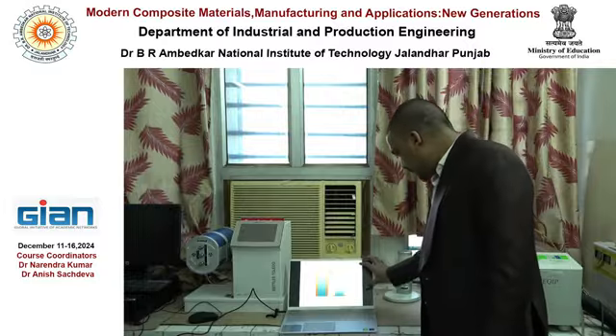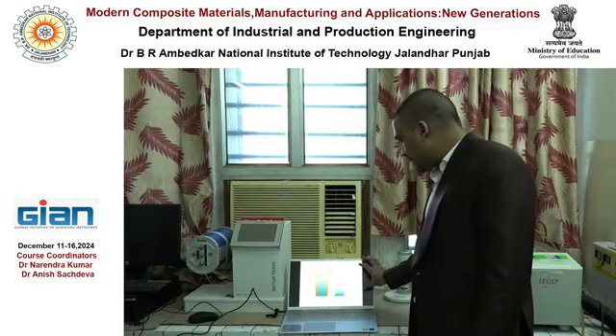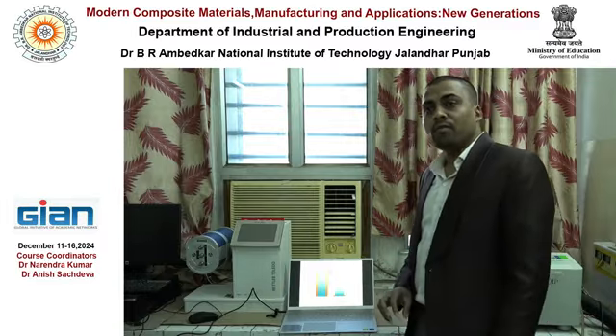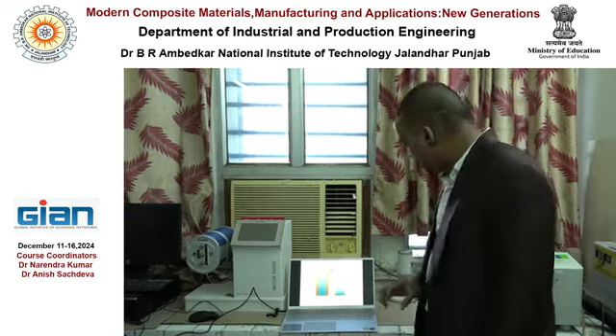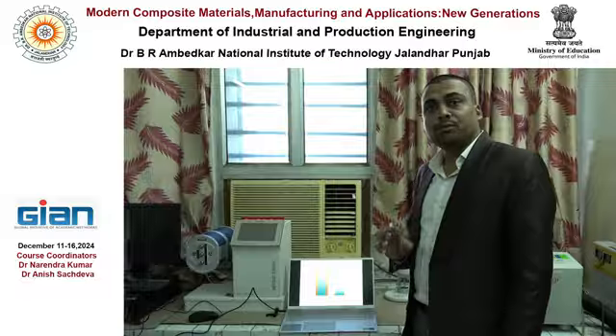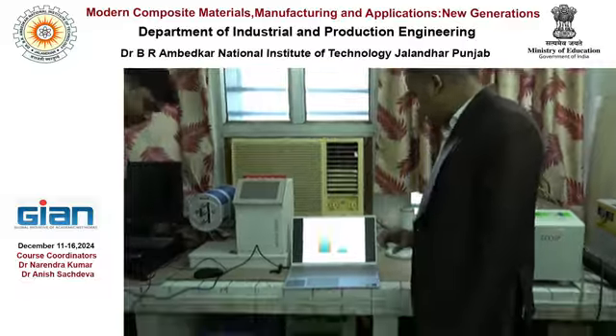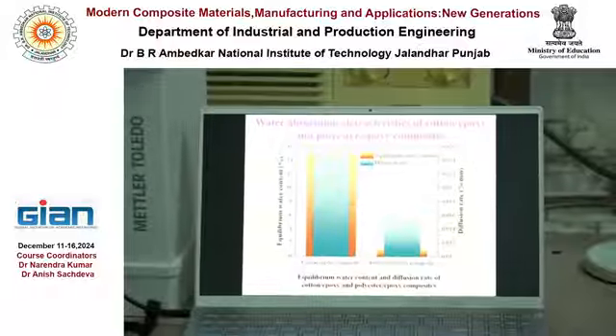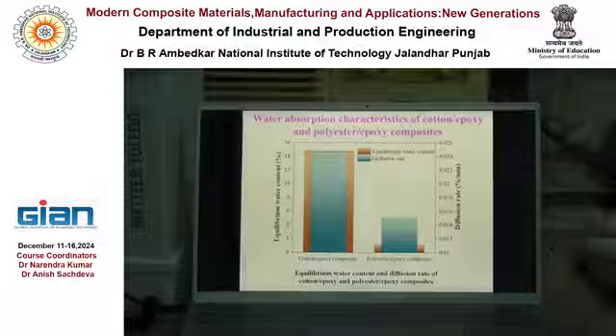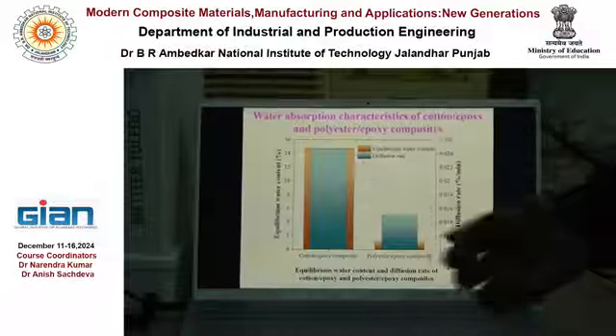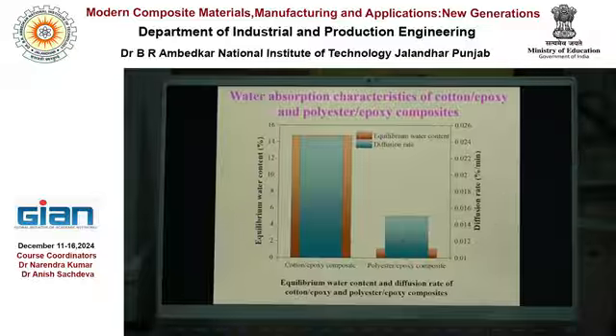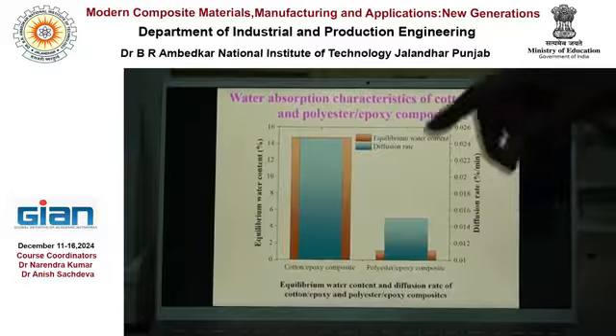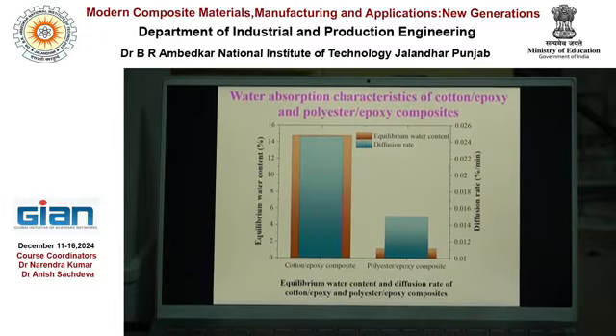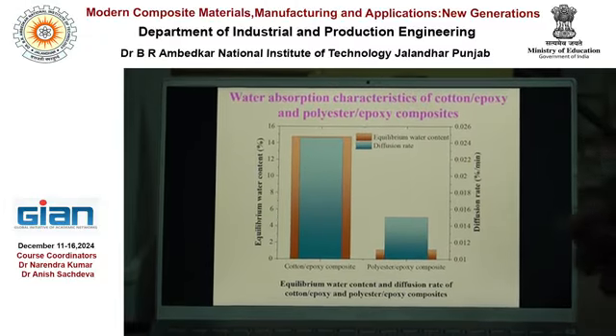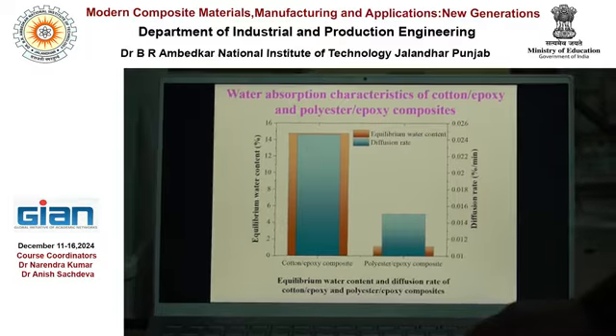Yes. This is the result of water absorption of cotton epoxy and polyester epoxy composites. In the water absorption test, we generally measure two properties. That is equilibrium water content, that is how much maximum water this composite can have at the time of saturation, and another one is the diffusion rate, at what rate your composite is absorbing the water. So these are again important.